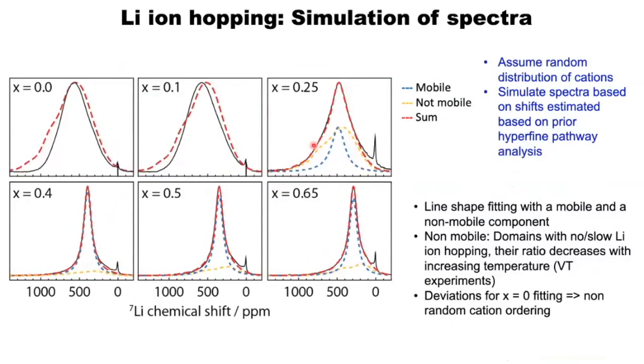This is a well-known phenomenon in NMR called two-site or multiple-site exchange, and the bottom line is we know how to model it. These are simulations done by Katerina, where she assumes, first of all, a random distribution of lithiums being surrounded by a random distribution of transition metal ions. She can then put in hopping between these sites and model the spectrum as you start removing lithium from the material. You can see that the spectra are well modeled by a model where you've got some rigid ions remaining, but most of them, by the time you've come to x equals 0.5, are mobile.